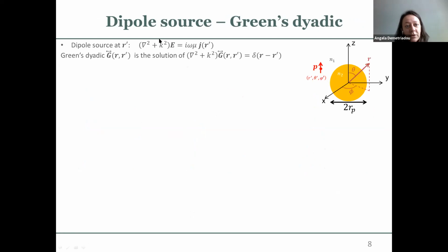So what I need to do is solve my Helmholtz equation, the inhomogeneous differential equation that I'm showing here. And the best way to do that is by obtaining my Green's dyadic, which is basically a generalized solution of this equation. And then from that, I can construct back my electric field by having a dot product between my Green's dyadic and the dipole moment of my emitter at that position there.